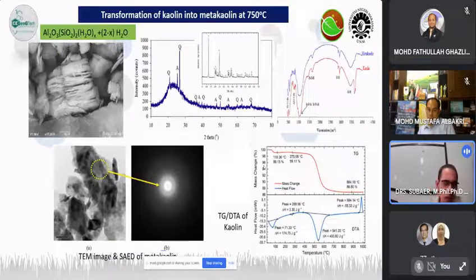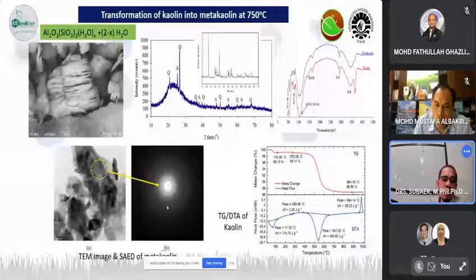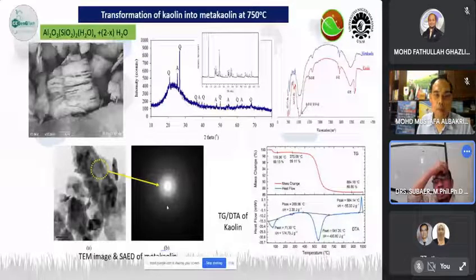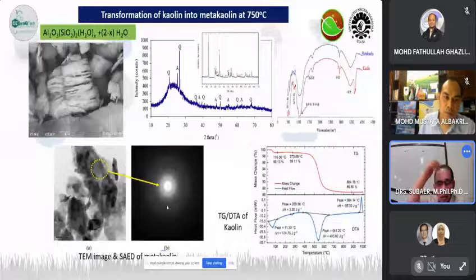And the electron diffraction. You see the kaolin morphology here, and then you take the electron diffraction, and you found that the pattern is only about rings,